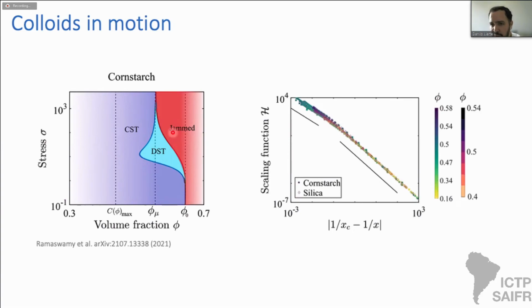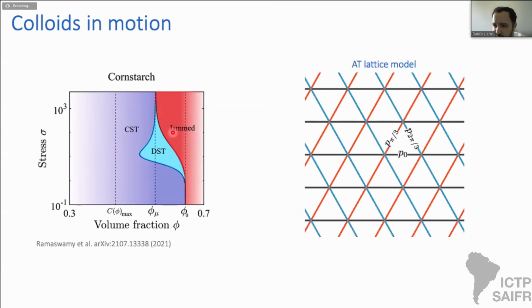but just briefly mention our attempt to tackle this problem using a microscopic calculation. An important feature in these systems is the formation of force chains, which lead us to consider the role played by anisotropy in the response of these viscoelastic materials. For this end, we can imagine populating bonds in a simple triangular lattice and having the probability depend on the orientation of the bond. We have been exploring both the phase behavior and dynamic response of this system. And without going into any details, we believe that the inclusion of microscopic mechanisms of anisotropy, along with other features that I have not time to discuss here, has the potential to clarify some of the deep questions regarding intriguing new results for shear jamming and thickening.